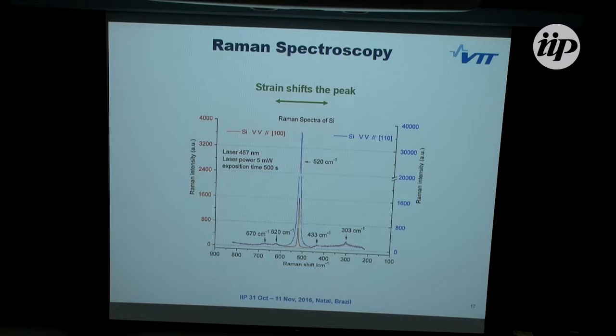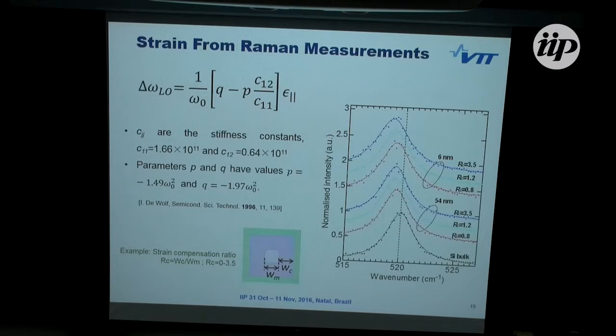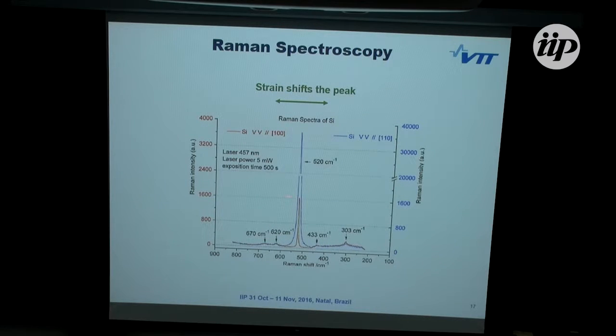So there's a very nice optical phonon peak at 520 1/cm wave number, and this peak shifts with strain. So we can measure the peak position, and then from there get the strain in the membrane.